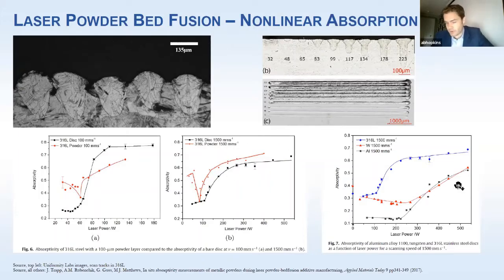Then over here on the right, I'm showing it's extremely dependent on the alloy. Not surprisingly perhaps, but if you look at aluminum here at the bottom, you're basically not absorbing at all. These are discs, by the way, not powders, but you'll have a similar shape for powders as to this 316L shape. And 316L is very different than aluminum or tungsten. They do eventually converge when you drill a deep enough hole, but obviously the physics are tremendously dependent on the alloy.